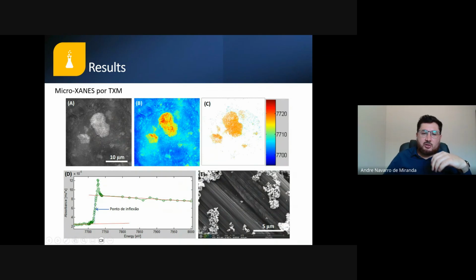So here we have the K edge of the cobalt. I will not explain this in depth, but here we can basically see the oxidation state of the cobalt: if it's cobalt 0, if it's cobalt +2, or if it's cobalt +3. So here we have three pictures. This is the texture of the catalyst. This is an agglomerate of cobalt particles, like here. Here's the concentration of the cobalt spinel. So we have an agglomerate here, and we have just some particles dispersed. And here you see the oxidation state of the particles. So we could see the oxidation state of the particles over the cycle of discharge and charge of this battery. So this was an operando experiment.